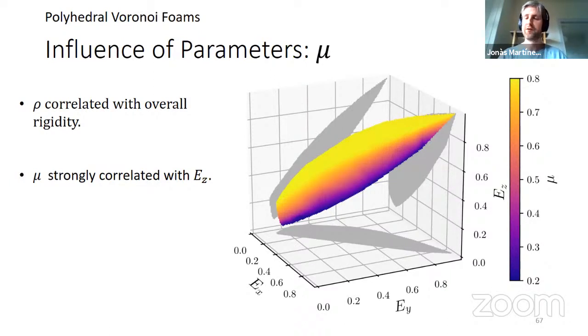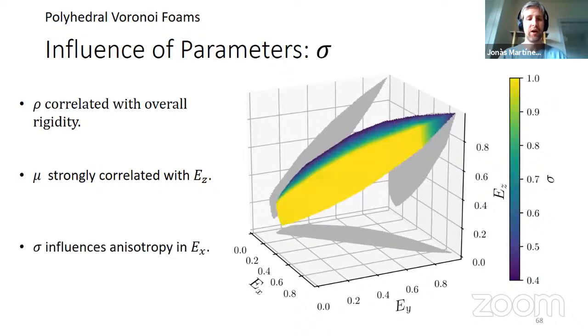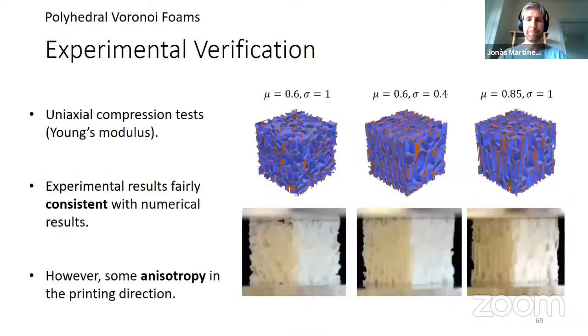So here you can see, for instance, the mu is correlated and sigma is correlated with it. And finally, like in the previous work, we did some experimental verification. And the results were fairly consistent, but I want to point out that it's actually very complicated to precisely determine the elastic behavior of materials made by fused filament fabrication, because there's a lot of factors impacting it.